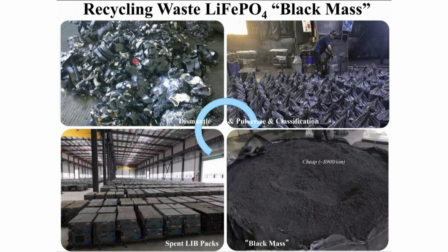and then it's separated into these electrodes which are connected to the current collector. So there is an issue of how to separate the active material from the current collector. And then after sorting, you can get this kind of cathode black mass or anode black mass and separator and so forth. But they are never very pure.